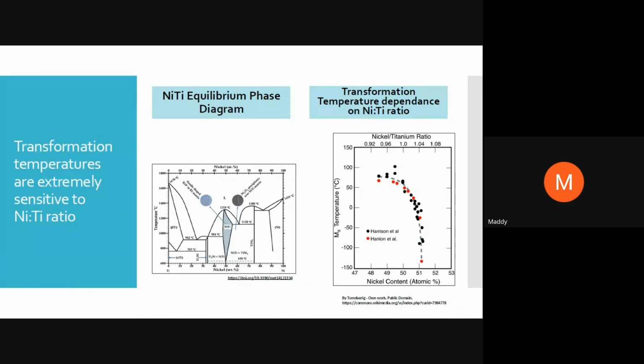So when somebody asks you a question, what's the chemistry of the NiTi alloy? It's very difficult to answer that. And rather, the question should be, what is the transformation temperature? So that's why if you look at the ASTM standards, F2063 and so others, they will insist on specifying the transformation temperature. Most of them go with austenitic start or austenitic finish temperature while specifying their alloy. So if somebody says, I can give you the chemistry of NiTi alloy, it would actually not make much sense for us, because of the sensitivity of these nickel-titanium ratios.